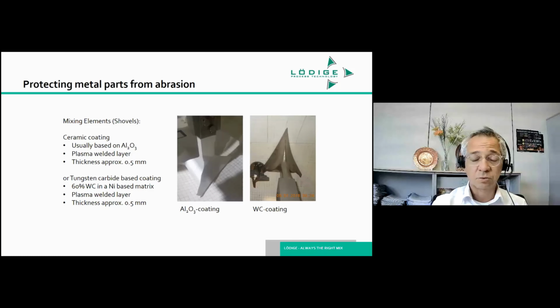Very difficult to keep the contour and to keep the tiles in place. So we found basically an aluminium oxide coating, a plasma welded application, allowing for a very thin layer of 0.5 millimeters, thus giving enough practicality to cover the mixing tools and keep the contour. This coating is good. It's very hard, but it has one drawback, that it's brittle.